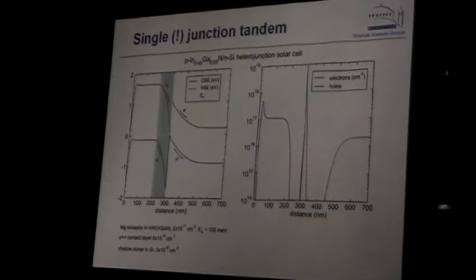So this is a very interesting concept. It's a single junction tandem. For any tandem, you normally have to have at least two junctions. And in this case, you have p-type indium gallium nitride on n-type silicon, and you have this large charge separation, because electrons are separated this way, holes are separated this way, and these holes are recombining with these electrons. This is potentially a very interesting concept. There is an issue with how the interface looks between indium gallium nitride and silicon, because these materials are not so compatible, but in fact there is quite good progress in this area.